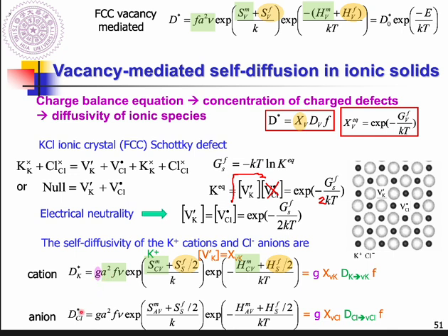And the same idea for chloride. You already write this down, just fill in each one. So this is the vacancy at the chloride side. The fraction will involve the Schottky defect formation Gibbs free energy, and separate them into enthalpy and entropy terms.